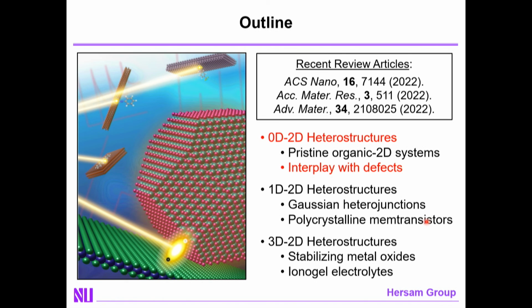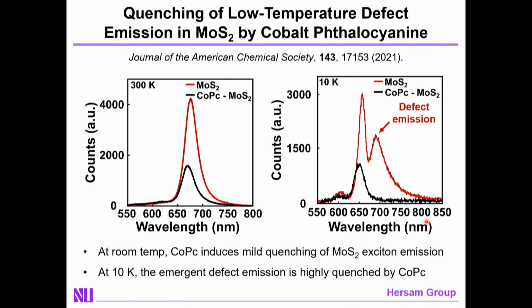For now, though, I'll only move on and give you another example of where a 0D, 2D mixed-dimensional heterostructure adds value compared to just the 2D system alone. For this, what I want to talk about is not the room temperature behavior, which I already described, but to observe what happens when we go to low temperatures. And in particular, if you take moly disulfide and you look at, for example, photoluminescence at room temperature, you'll see one clear peak, which you can attribute to excitonic effects in the moly disulfide.